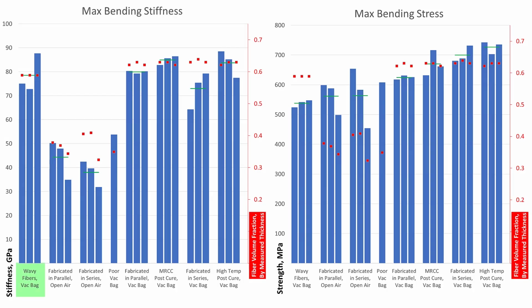The samples with misaligned fibers did not have definitively lower stiffness than the other vacuum-bagged samples, but did have the lowest strength.